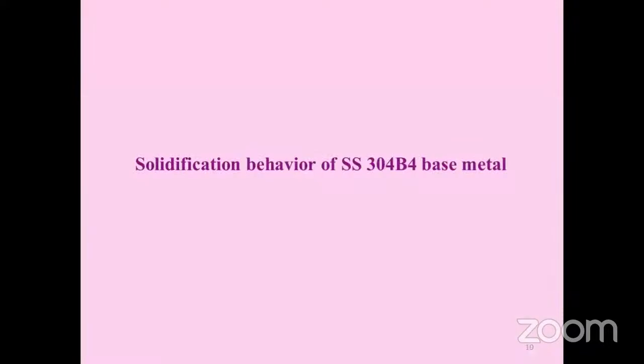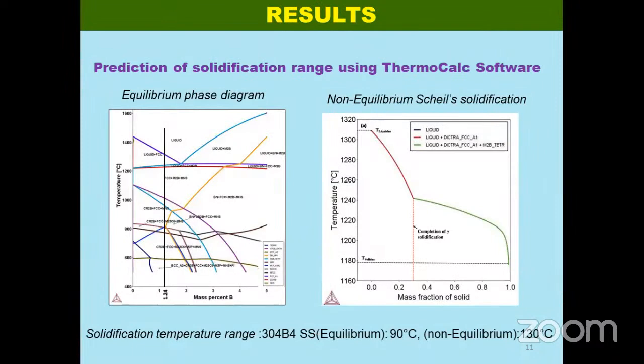Now coming to the borated stainless steel base metal, for this material we have simulated some solidification behavior using Thermo-Calc software. Here is the equilibrium phase diagram calculated for this particular composition with 1.24 weight percent of boron. Here we can see that the solidification range is very narrow. But when we go for a non-equilibrium solidification simulation, as in the case of weld metal, which undergoes fast heating and fast cooling, the solidification scheme adopted is a non-equilibrium process. That is, there is not sufficient time for diffusion of all elements to take place during solidification. So there is a lot of segregation involved in this solidification process.